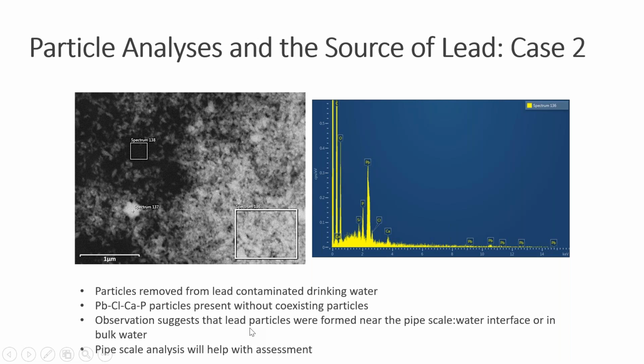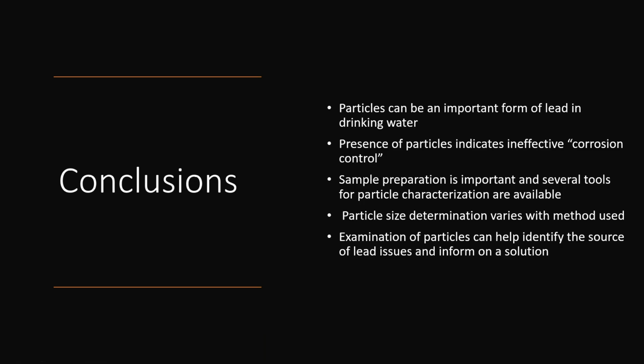And so what does this suggest? Well, this might suggest something quite a bit different: that these particles are forming more so in the bulk water or at or near the very surface of the pipe. It's not really an issue of a pipe scale falling apart or sloughing off, but rather particles being formed in situ somewhere that are just being picked up and moved along in the water to the sample at the tap. So again, pipe scale analysis will certainly be helpful in understanding this, but you can see the kinds of differences that we observe in these practical samples.